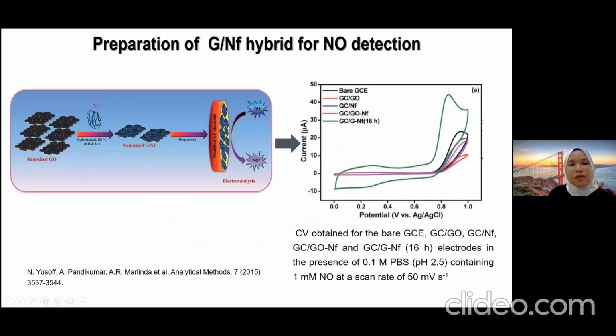Okay, and then there is a second example: preparation of a Graphene-nafion hybrid for detection of nitric oxide as well. So we are using the hydrothermal method to hybridize graphene oxide and the nafion. And then later on, we are using this modified electrode to detect the nitric oxide. So again, you can see from the CV here, the hybrid Graphene-nafion showing the highest detection in current for nitric oxide.